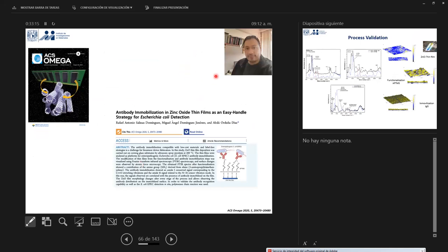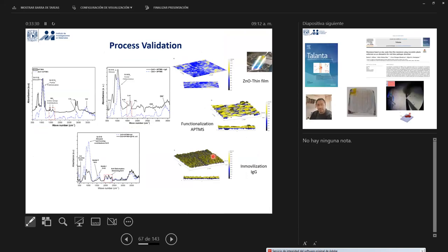In this case, we have a new postdoc in our group, Dr. Rafael Antonio Salinas. He did some work in his PhD and developed biosensors for detection of E. coli and salmonella pathogens. He grew zinc oxide thin films and checked the FTIR spectra of these thin films before and after interaction with the bacteria. He found that in techniques like FTIR the peaks were changing, so there was some successful interaction.